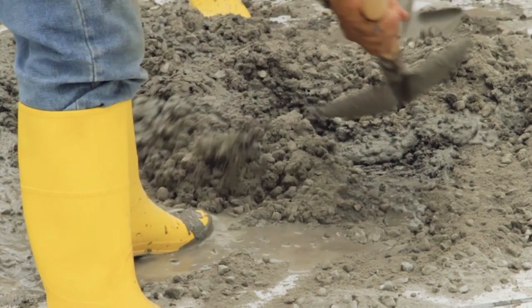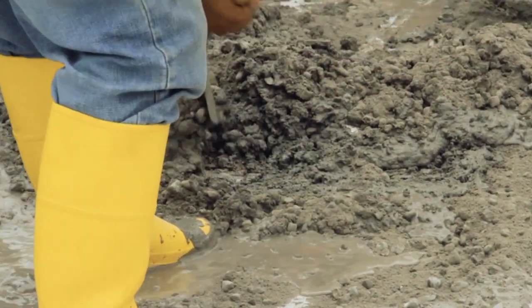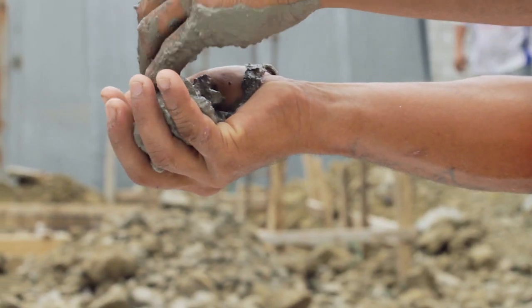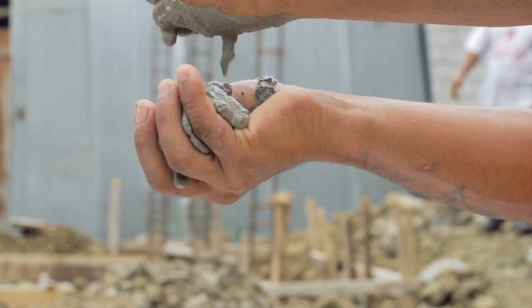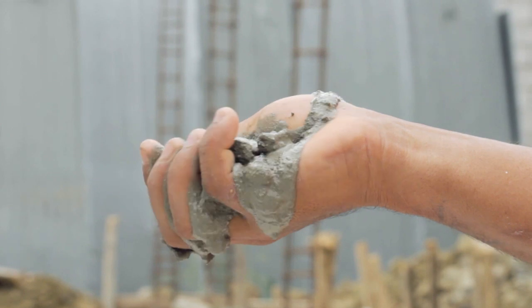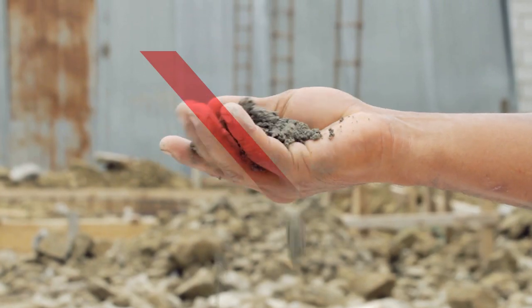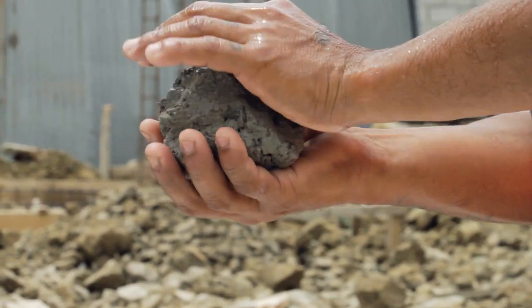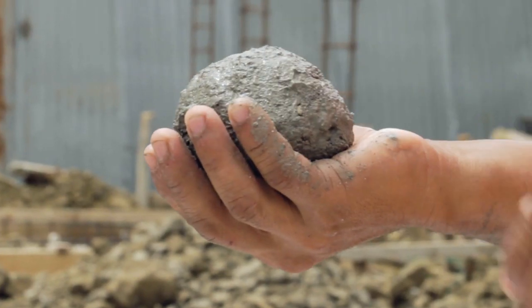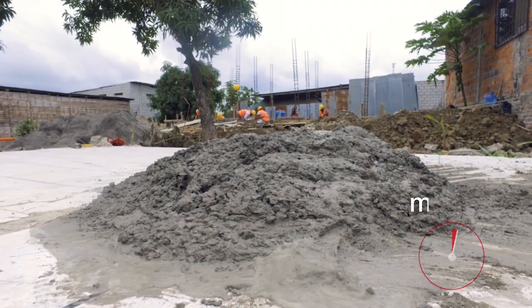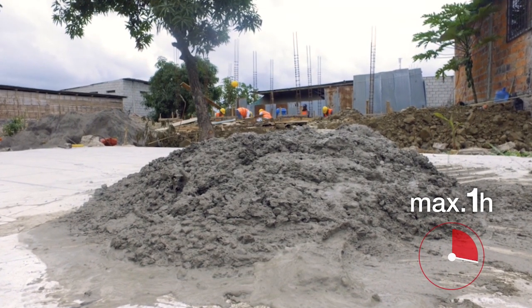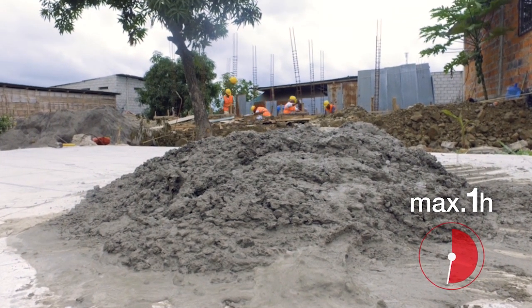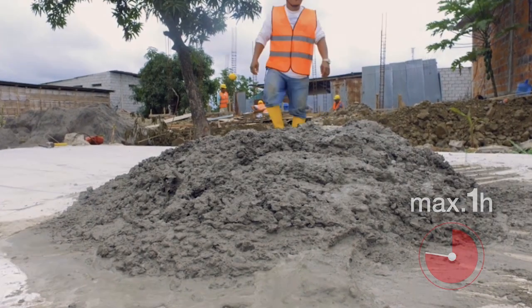Concrete test. The following test can be made to check that the concrete mix is optimal. Take a handful of concrete. If the concrete leaks through the fingers, the concrete is too wet. Concrete is not good either if it is too dry. It should be possible to make a ball with the concrete. Concrete must be used in less than 1 hour, otherwise it might start to harden or it might lose water by evaporation.